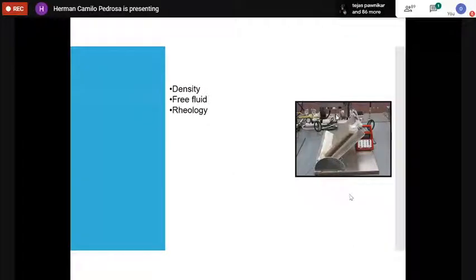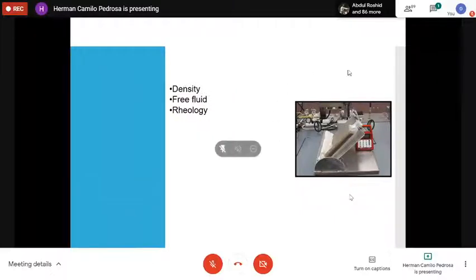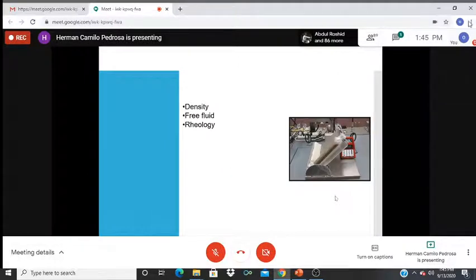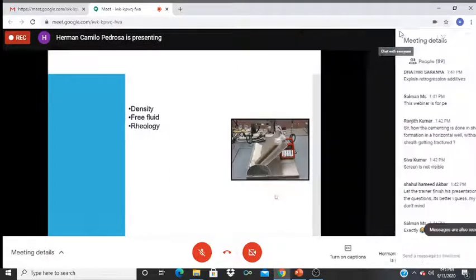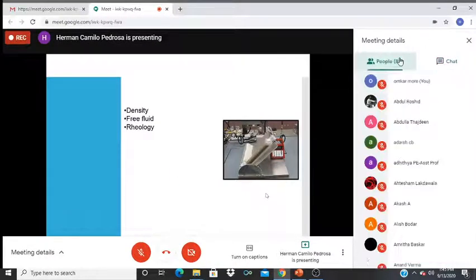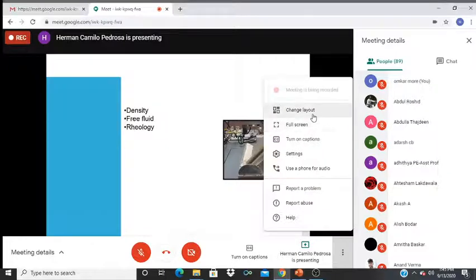Then we have the rheology. The rheology will help us to know the viscosity of the cement. As I mentioned before, the ECD is something really important for us. If we have a high ECD, we can damage the formation, and a way to increase that ECD is with higher viscosities. So if we have a really high viscosity in the cement, we may have that kind of problem.